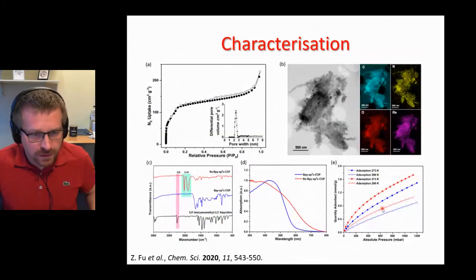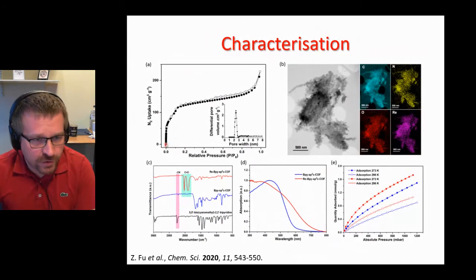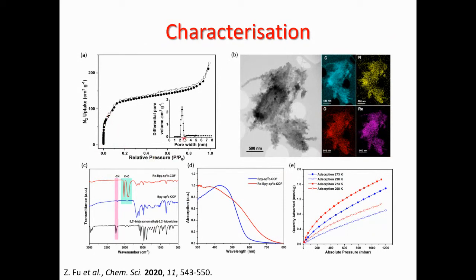These materials then are highly porous. They show a large uptake of nitrogen, a large step here, which indicates microporosity, and the pore width really matches what we expect from the XRD patterns. And looking at EDX mapping, we can also see that the elements are there, of course, as you expect as building blocks in the material itself, but also the rhenium remains quite evenly distributed throughout the system. So we don't get too much detachment or aggregation of rhenium. It seems like it's a complex formed in the solid state, effectively.